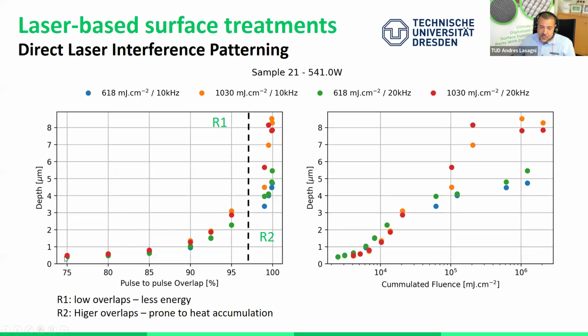So now, of course, it's clear we are using more pulses if the overlap is higher, so the structure gets deeper. Here we have started to observe at very high overlaps some interesting results that we will come to quite soon. And we can also make this diagram as function of the total energy that we use to irradiate the material. We observe here at the beginning also a similar trend, and then for very high cumulative fluencies, there is some randomness about the results.